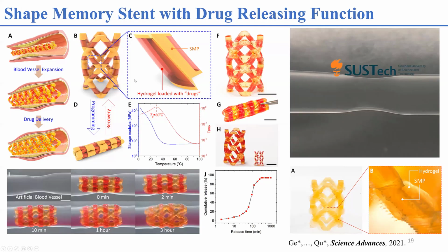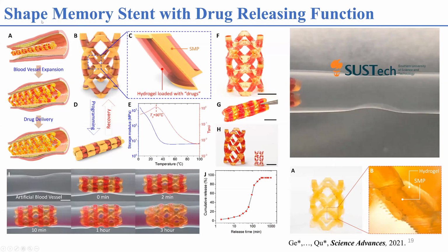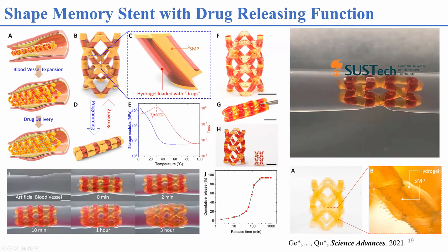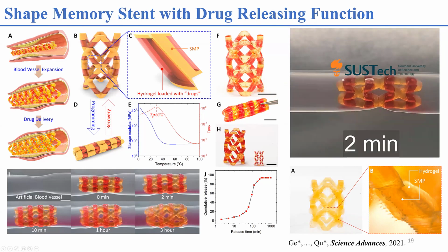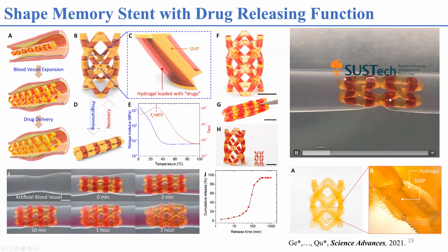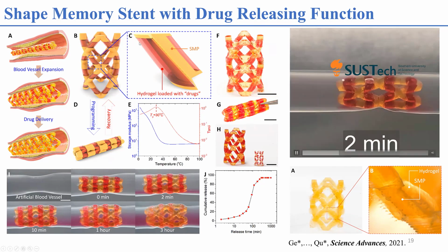Another example is that we can combine the hydrogel with shape memory polymer. We can print a shape memory polymer stent for cardiovascular application, and then we add the hydrogel onto the rods of the stent, and the hydrogel can be used for drug releasing. Therefore, we have a stent which is not only able to expand and open the narrowed blood vessel, but the hydrogel will also release the drug. Therefore, we add two functions into one stent.